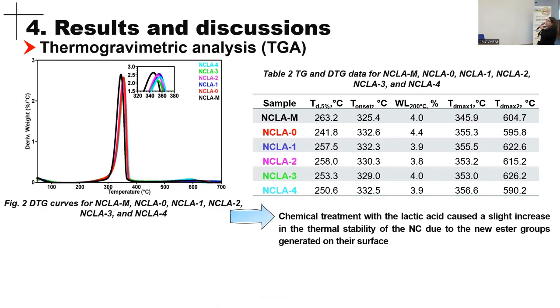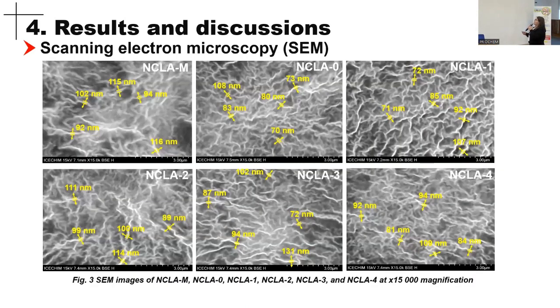This might be because of the new ester groups generated on the surface of nanocellulose, which are known to be more stable against the thermal degradation. The scanning electron microscopy showed that both the control sample obtained in the presence of hydrochloric acid and the samples obtained in the presence of lactic acid present diameters in the nano range.